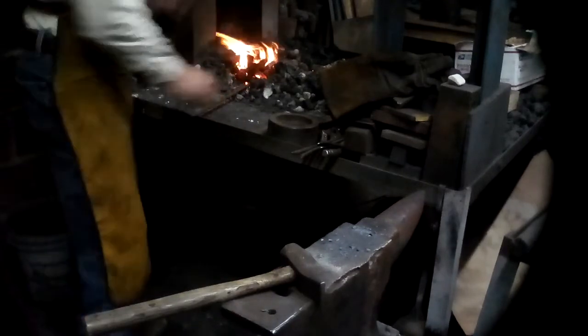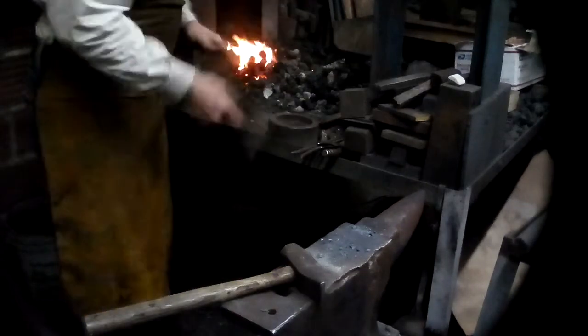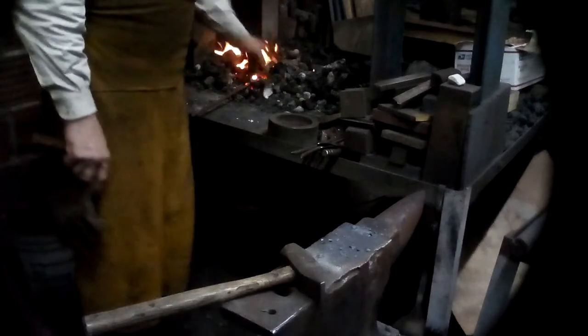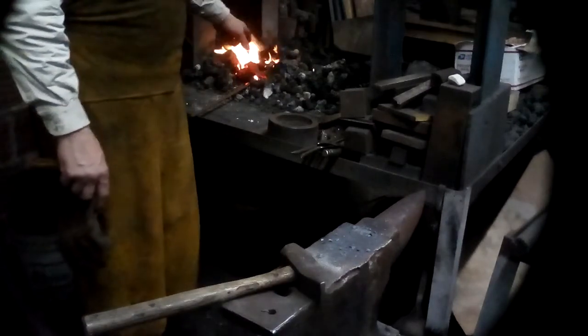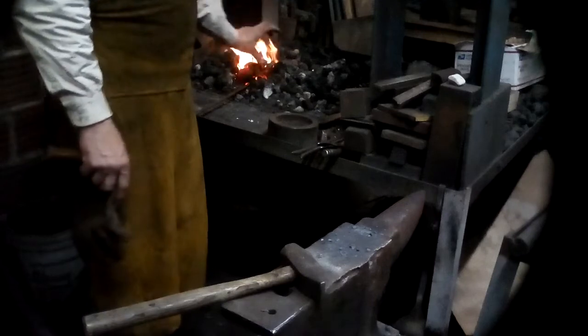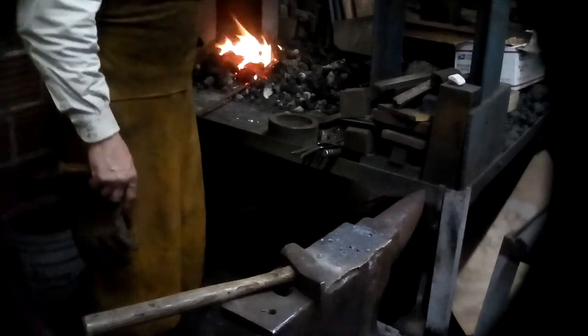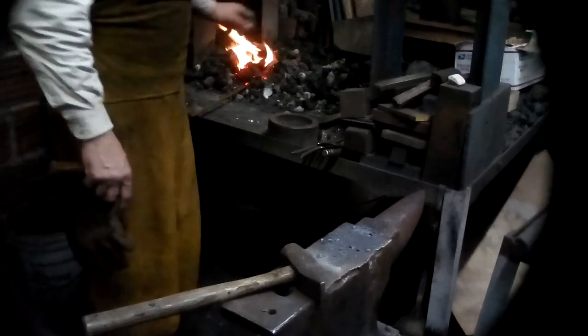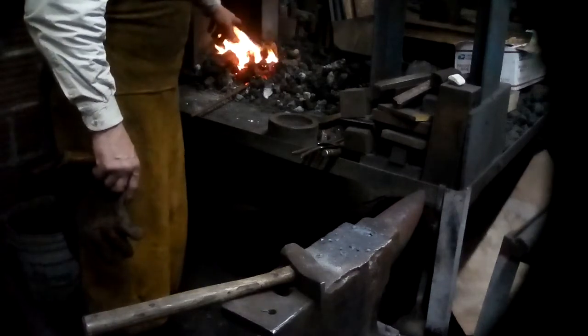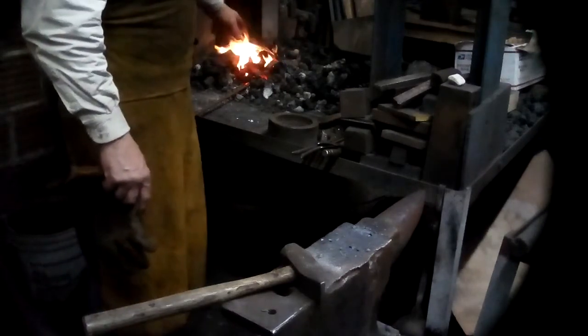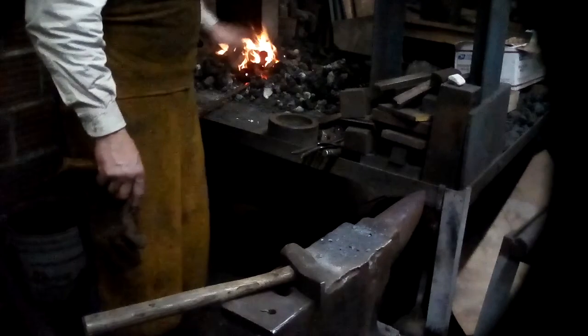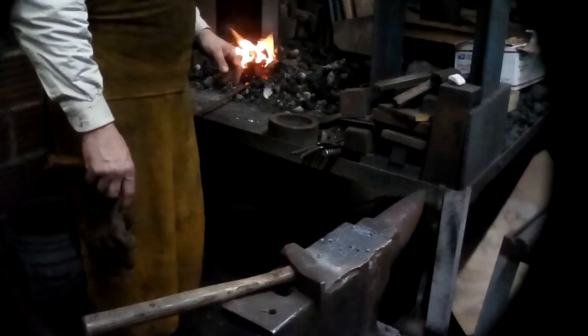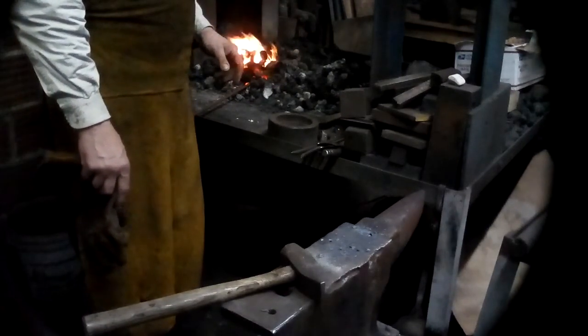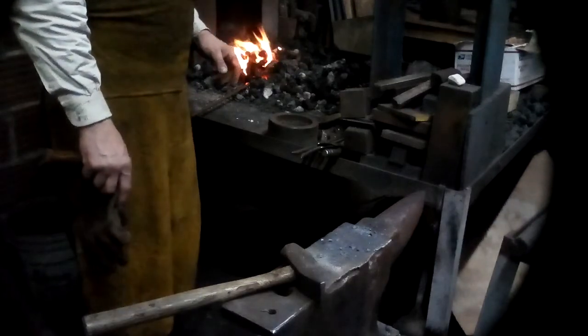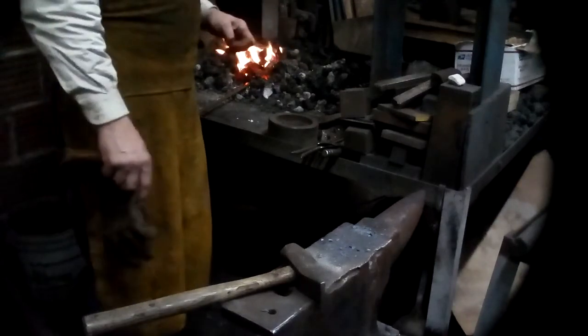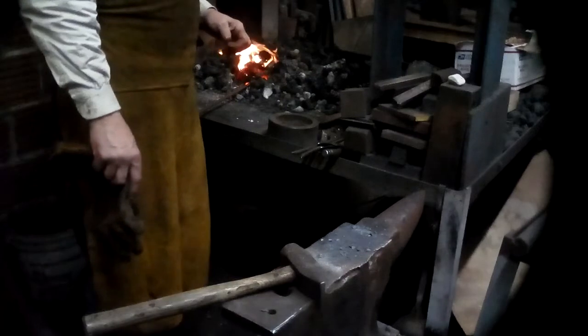Just like in a cutting torch, down near the bottom you have an oxidizing layer of the fire, then you have a neutral part of the fire in the middle, and then at the top you have a reducing layer. And when you're forge welding, you should have a fire that's deep enough so that when you're level in there, the zone that your work is in is either neutral or very slightly reducing. If you're in the oxidizing area, there's a good chance that you'll start to burn the metal even if you've got flux.